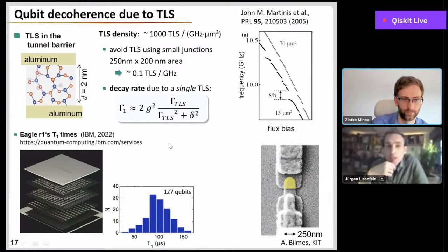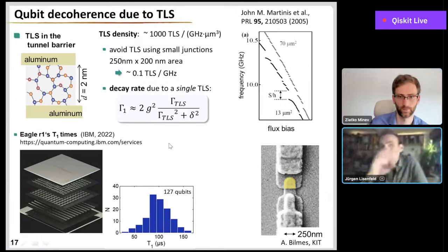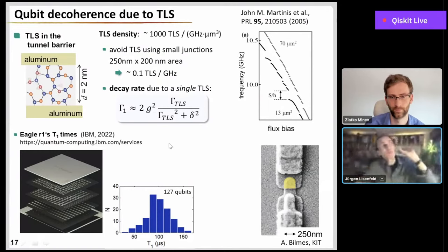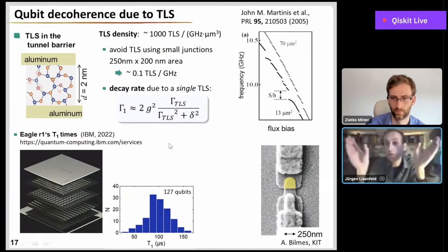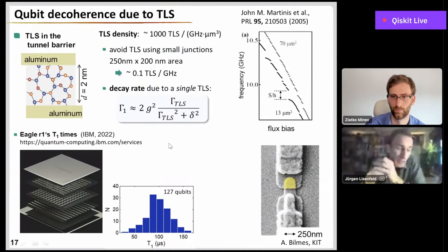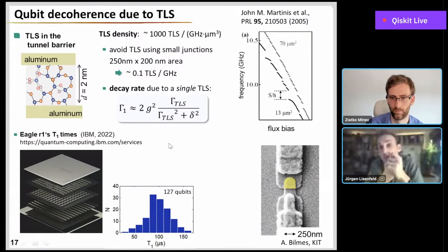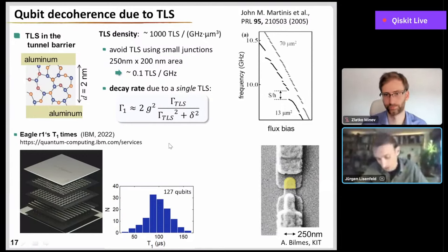Yeah, like all other parameters of the defect, like dipole moment and so on and so forth, this is, of course, a distribution of possible T1 times in this model. And actually, the theory says that there should be a maximum for the probability to have short lifetimes and another maximum to have rather long lifetimes in these defects. The defect lifetime, of course, also depends on the density of your defects in the material. The more you have, the more likely it is that they just interact, and each of them would then probably achieve a shorter T1 time. But it's true that there are also longer living defects. And I can tell you from my experiments, where I have measured maybe a few hundred defects already within different qubits and materials, the best that I found was a 10 microsecond T1 time, which was a single occasion, basically.